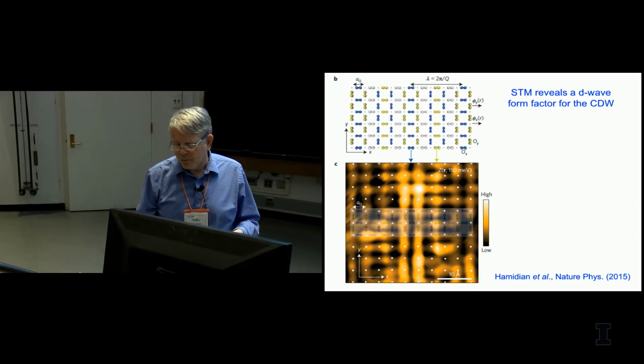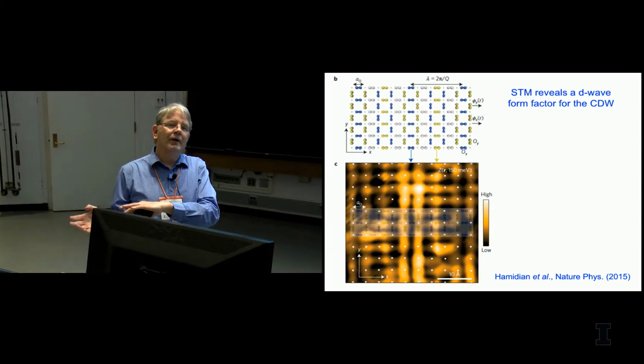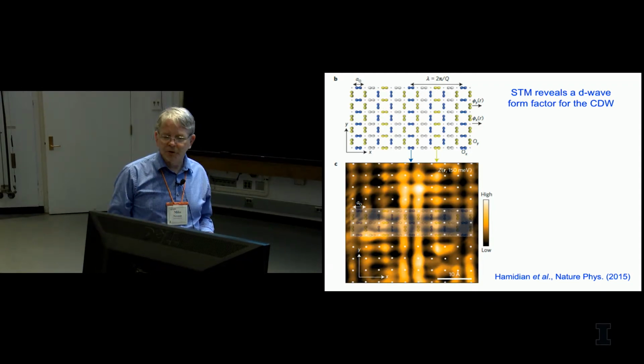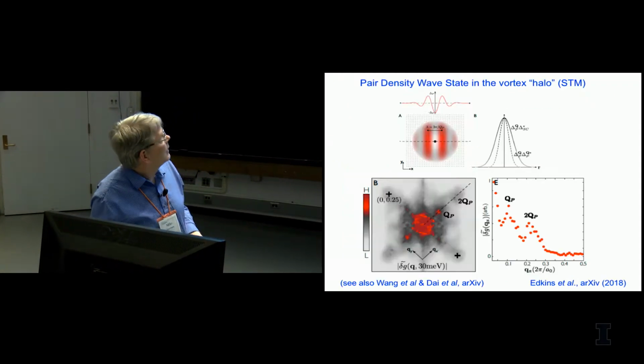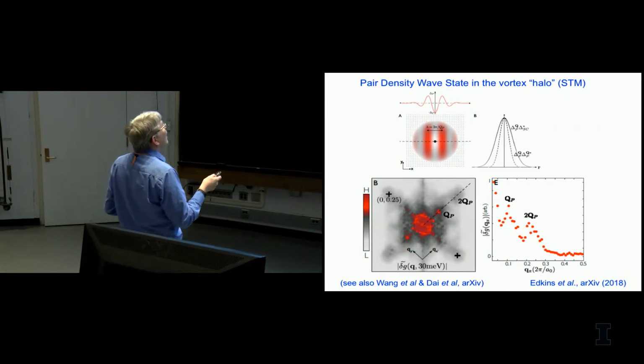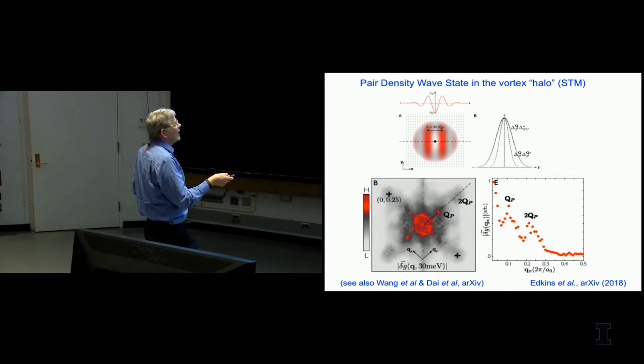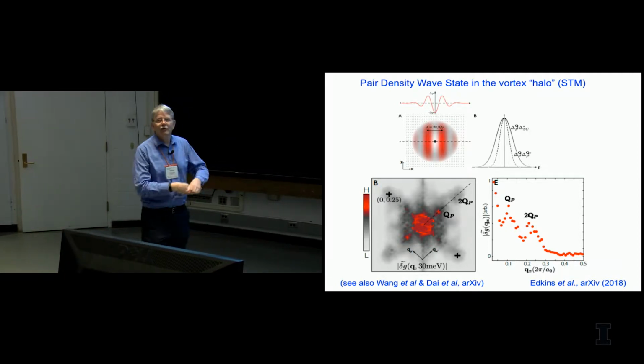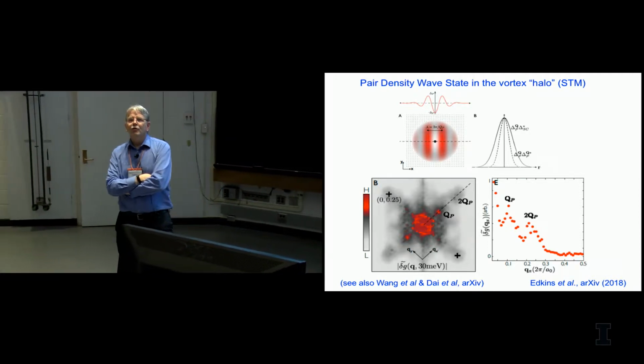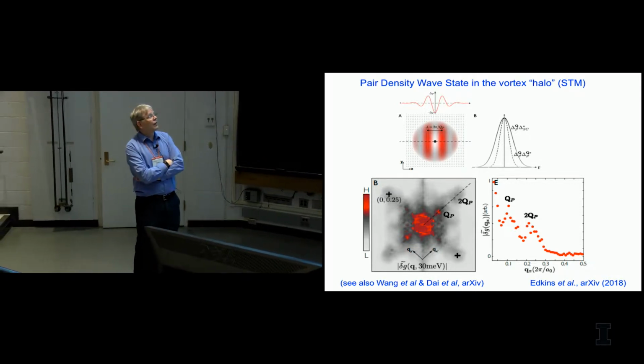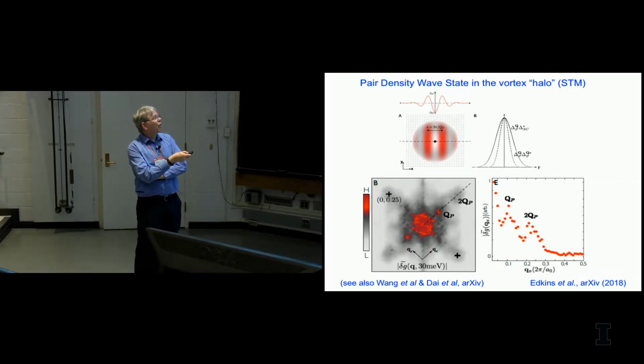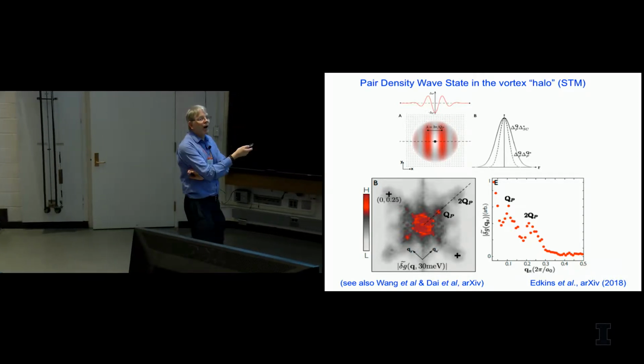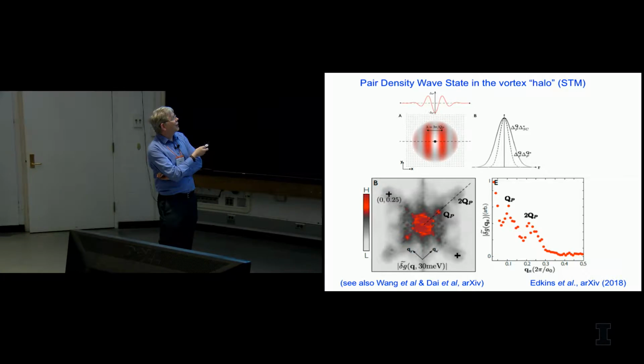And so there have been a lot of theories about the relationship between this D-wave form factor and whether this is a particle-hole mirror image of the D-wave superconductor. And then most recently, there's been evidence from a preprint that came out a couple of months ago that in fact you might have a so-called pair density wave state. That is a superconducting state which is modulated in space with a wave vector half of what you see in the charge order. And one of the speculations is that in fact the charge order is secondary, and the pair density wave state might be the primary order parameter, and the CDW state is just a secondary consequence of this.